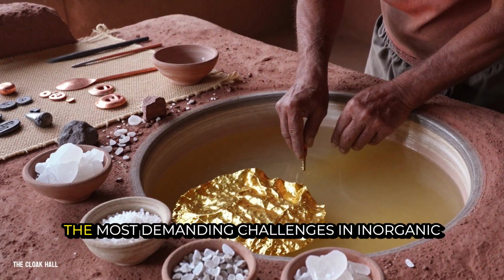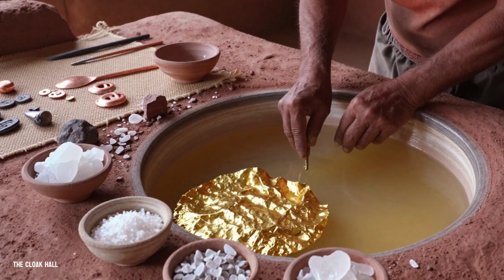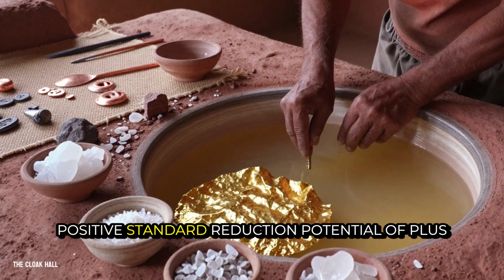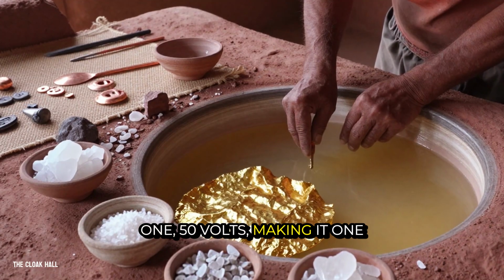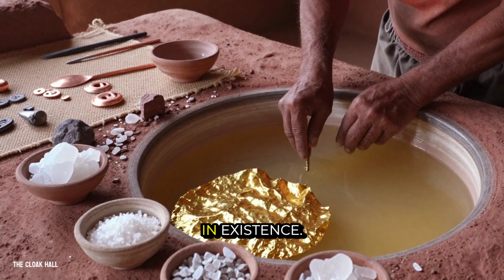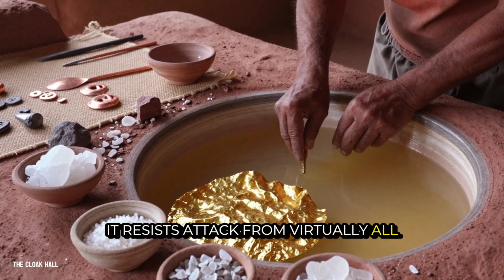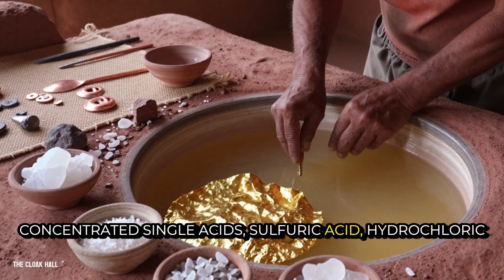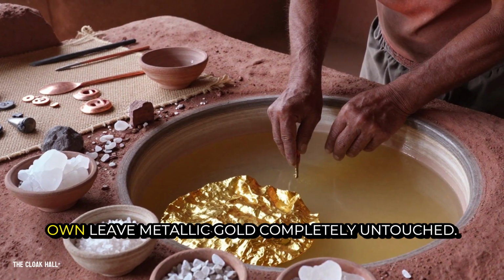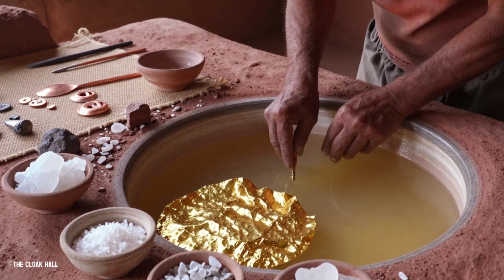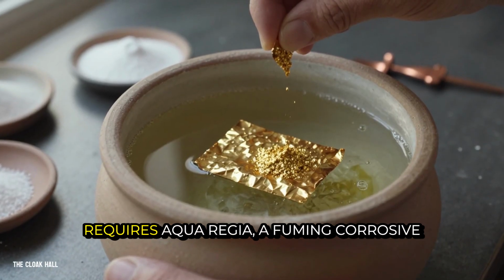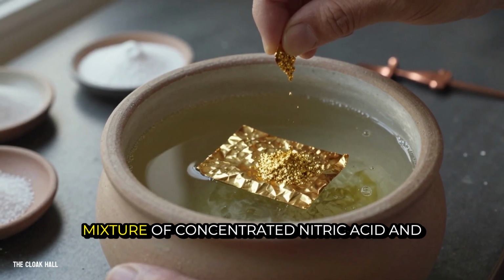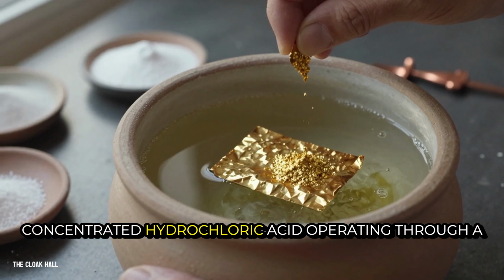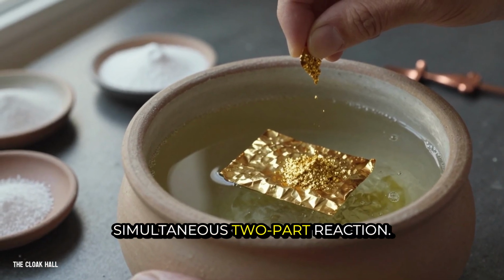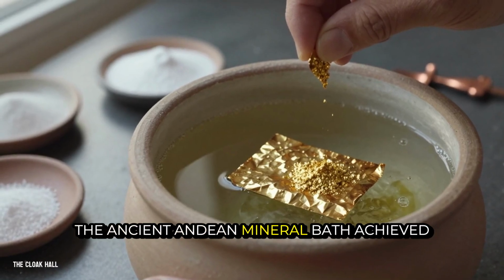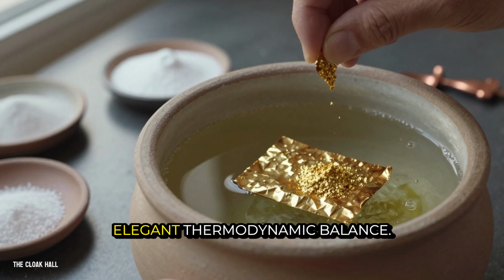Dissolving metallic gold is one of the most demanding challenges in inorganic chemistry. Elemental gold possesses an exceptionally high positive standard reduction potential of +1.50 volts, making it one of the most chemically noble elements in existence. It resists attack from virtually all concentrated single acids; sulfuric acid, hydrochloric acid, and nitric acid on their own leave metallic gold completely untouched. In modern laboratory practice, dissolving gold requires aqua regia, a fuming, corrosive mixture of concentrated nitric acid and concentrated hydrochloric acid, operating through a simultaneous two-part reaction. The ancient Andean mineral bath achieved this exact chemical feat through an elegant thermodynamic balance.